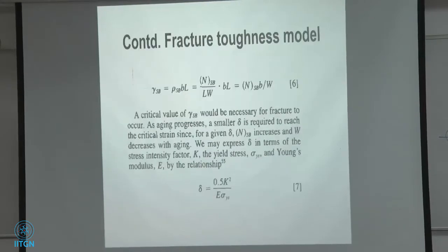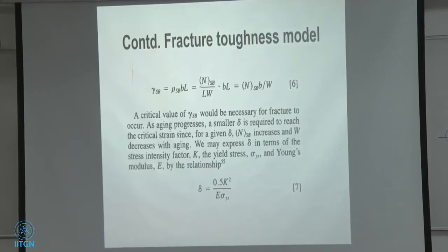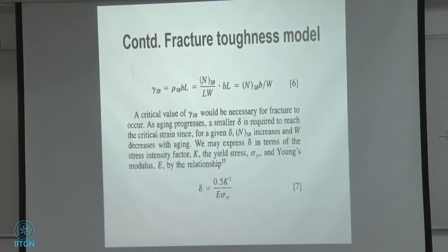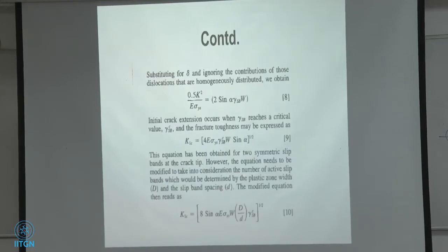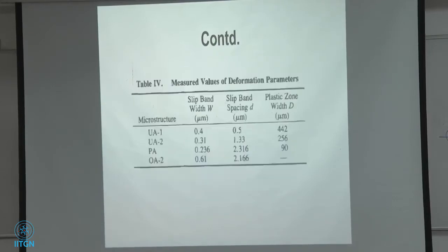So density of these dislocations and all this stuff, okay. Anyways, we come up with this, then we go back to our crack tip opening displacement, which is K squared divided by Young's modulus, times yield stress, and we come to this K1C is equal to, in terms of the dislocation, slip bands, widths, and all that stuff. So I put everything down here, okay? Also, I put down here the plastic zone width parameters, plastic zone width calculation, D.